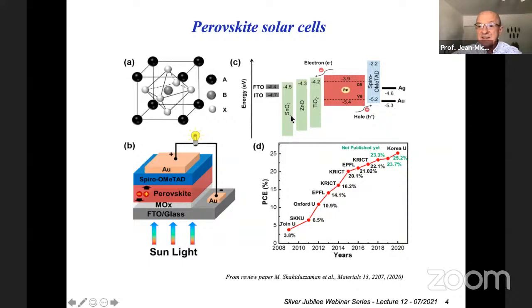These materials need to be sandwiched between layers to collect electrons and the holes. So a typical structure is a transparent piece of glass, which is coated with a conducting material. Here it is FTO, which is fluorine doped tin oxide. And we deposit on top an electron transport layer, so it is a metal oxide typically. The perovskite, which is a methylammonium lead iodide perovskite.